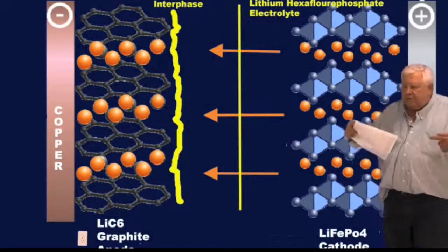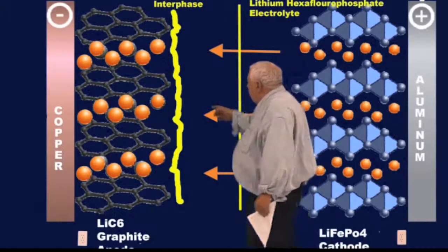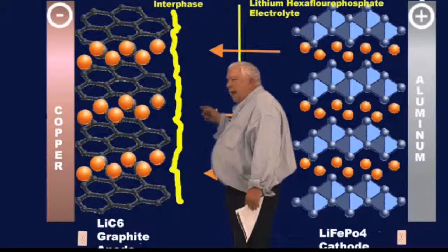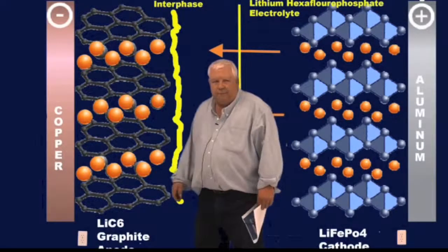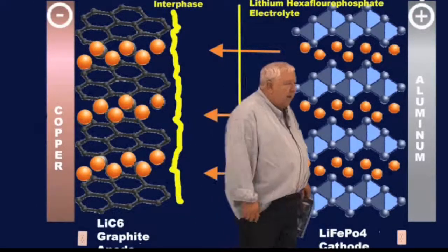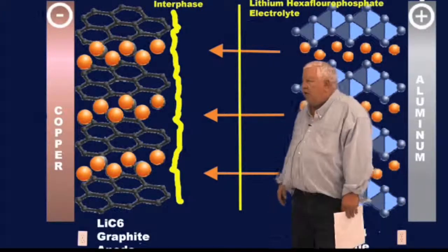And so we have 2 needles growing toward each other that are really only separated by a 3 mil plastic garbage bag. If they puncture it, they short the cell, and it discharges completely through there in a kind of violent display of current.